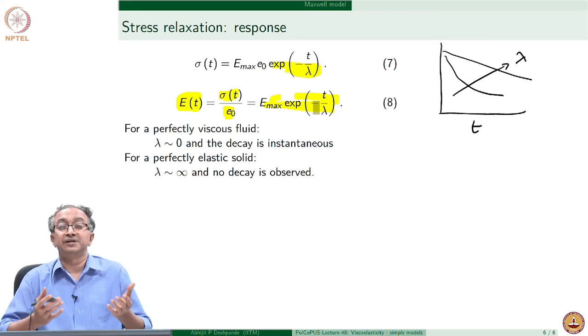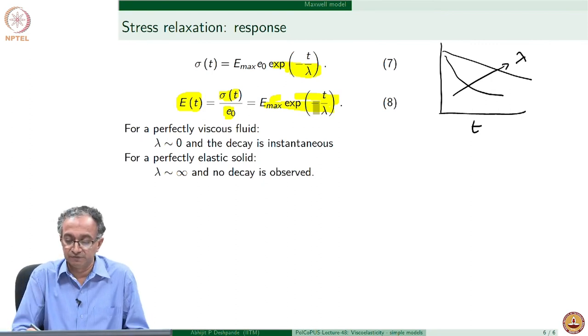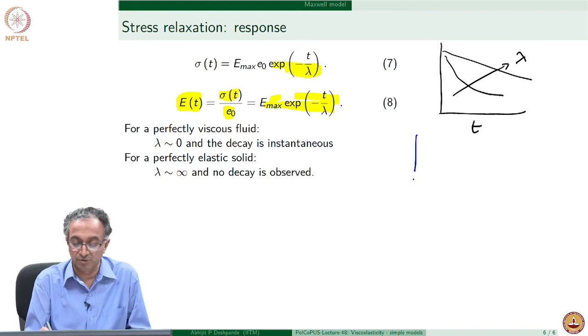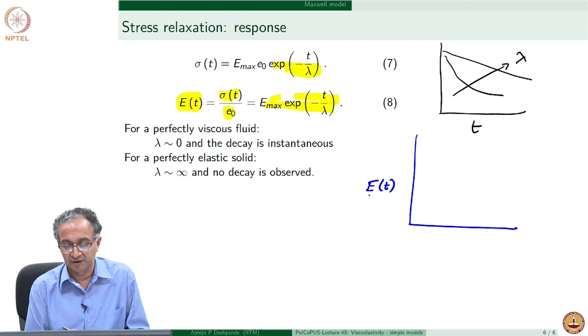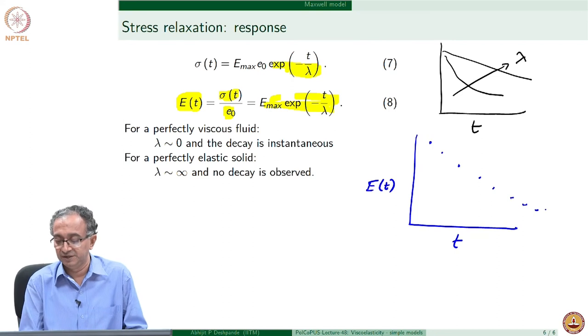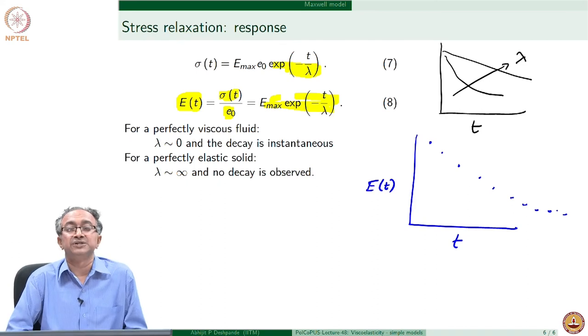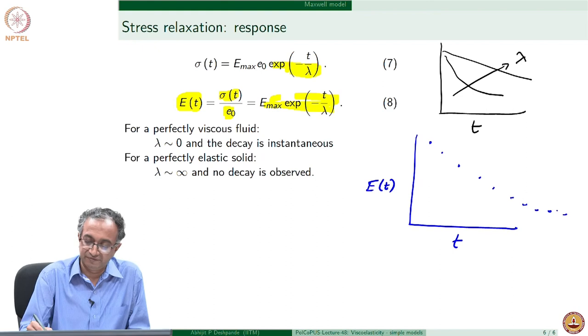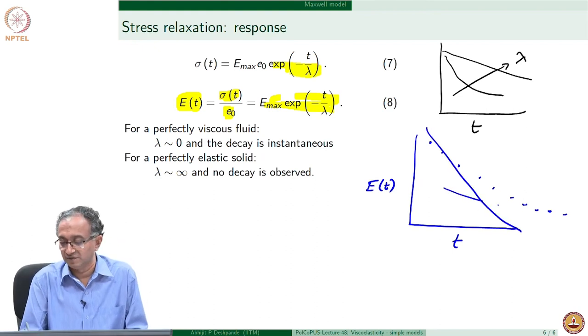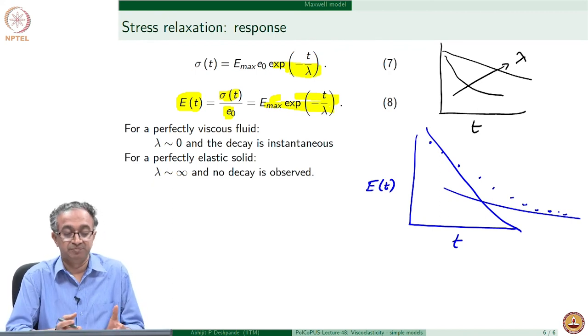The challenge is: when I do an experiment on a real or new material and measure its relaxation modulus, how do I rationalize its response? For example, if I measure the relaxation modulus for a new material chosen for an application and the data seem to indicate some decaying variation, I can try fitting an exponential. If I can only fit part of the curve, I clearly know that a single exponential is not sufficient to explain the behavior of this real material.